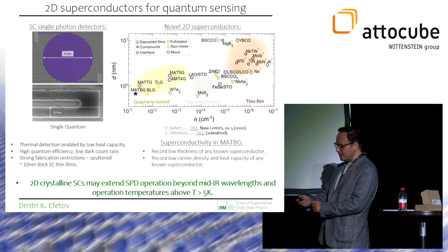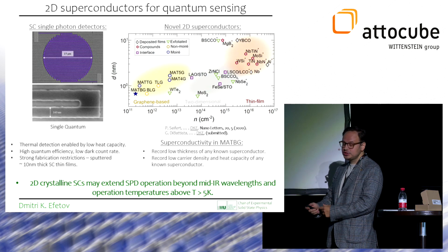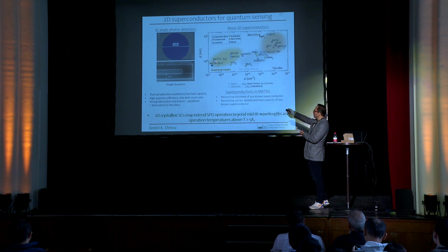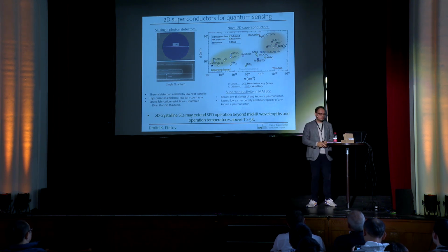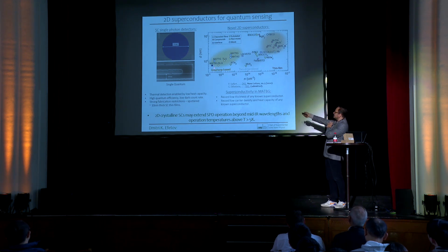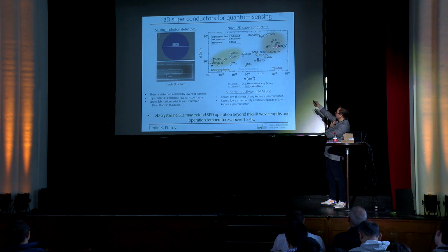And so here, graphene has a remarkable property. This was already discussed in Pablo's first paper on twisted bilayer graphene: the carrier concentration of magic angle graphene that gives rise to the superconducting state is extremely low. It's record low, in the sense that it's orders of magnitude lower than that of traditional superconductors like aluminum, niobium, and many more.